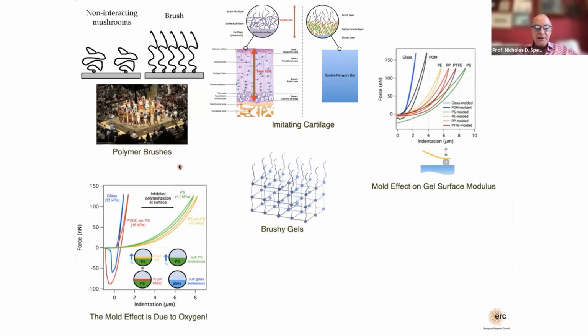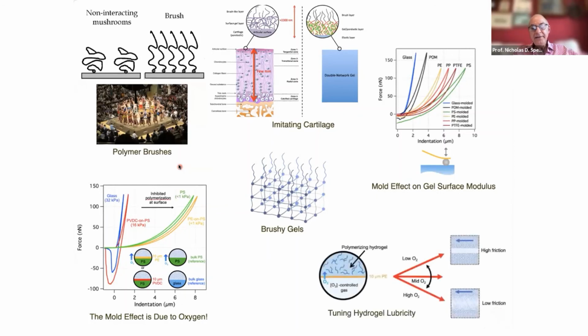An explanation that it's not due to the hydrophobicity of the mold, but due to the amount of oxygen coming out of the mold and to some extent the rate at which it comes out of the mold. And finally, how this can be used in order to tune the lubricity of hydrogels by tuning the amount of cross-linking in the outer surface of the gel during polymerization.